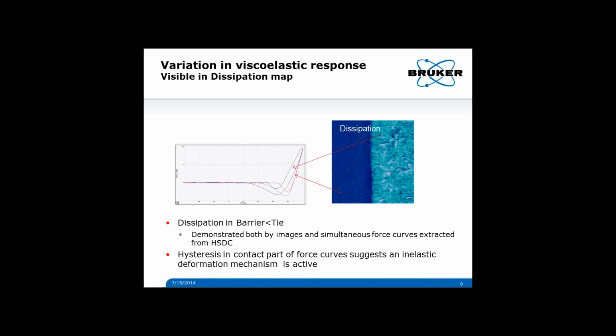And so we believe what's going on here is that there's actually a difference in the dissipation within the material, or a viscoelastic signature of the tie layer that's showing up here. When we do our modulus calculations, we don't have an inelastic deformation mechanism in that calculation. It's just the DMT model, so it wouldn't show up necessarily in the modulus, but we can see it from the dissipation channel here.